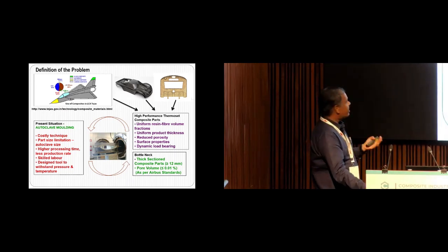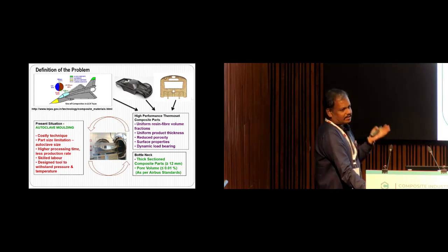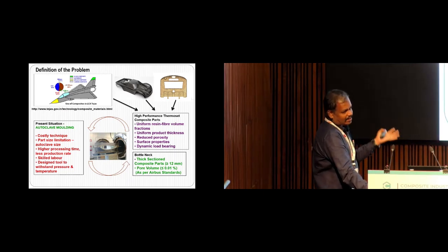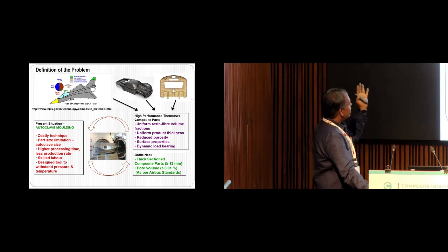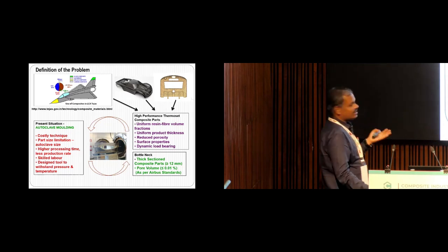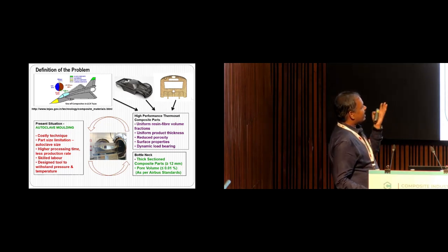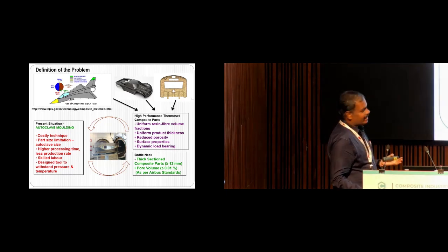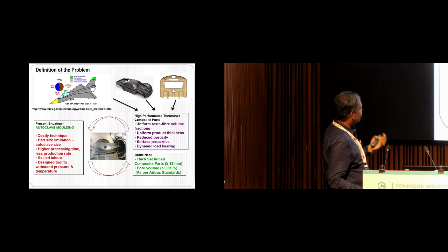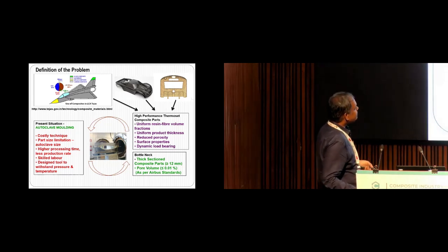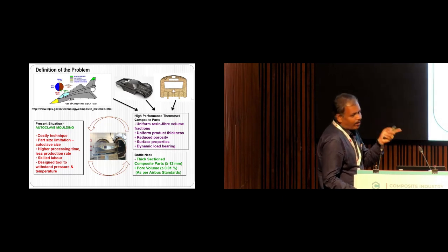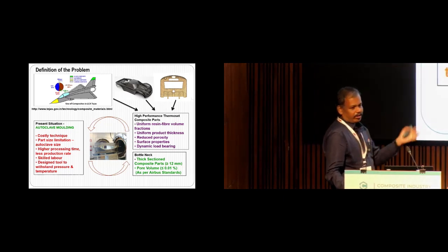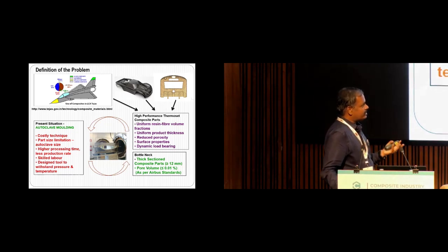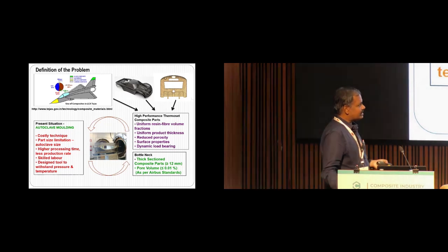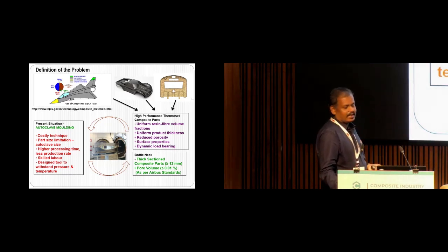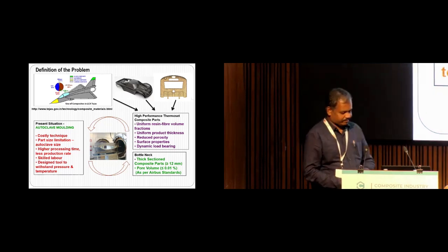But the problem with autoclave molding is it is a costly technique and it has part size limitation, because you can maximum manufacture a part of the size of the autoclave. Next, it requires higher processing time and has lesser production rate, and you need skilled labor and a skillfully designed tool to withstand pressure and temperature. So obviously, when you manufacture a composite laminate for aerospace structures, you should have uniform resin fiber volume fractions, uniform product thickness, reduced porosity, surface properties, and dynamic load bearing capacity.